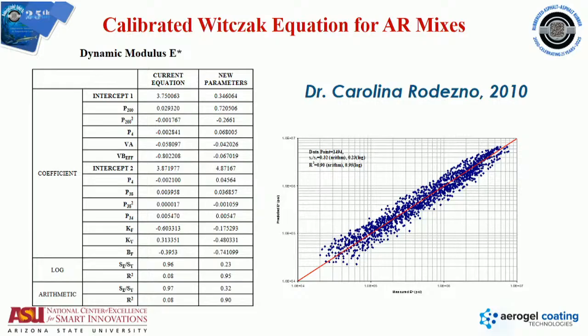Some of us, actually there are a couple. What's the other Witczak equation, Krishna? There's a shell equation people use for dynamic modulus. So we use the Witczak equation. Our previous mentor, who passed away, developed a prediction model for dynamic modulus. So we can do that for gap-graded mixes. It's available out there. You don't have to do testing. You can predict the approximate numbers and use them. And again, great result. The equation has been calibrated specifically for these types of asphalt rubber mixes.